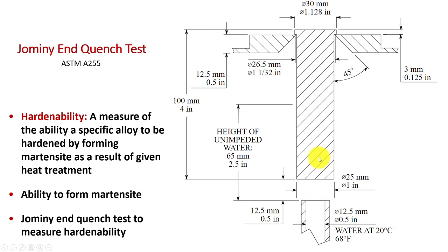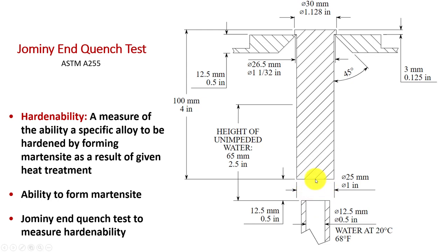Without the sample in there, the water is going to shoot up two and a half inches past this nozzle. For this one inch diameter sample, the nozzle needs to be at half inch from this surface — so we have a half inch gap. This is going to maintain constant flow rate and cooling action. We're going to cool that metal from the bottom and let it cool over time through the rest of the bar. This is going to take probably over 30 minutes. You're going to see a nice umbrella of water being developed as we quench that material.